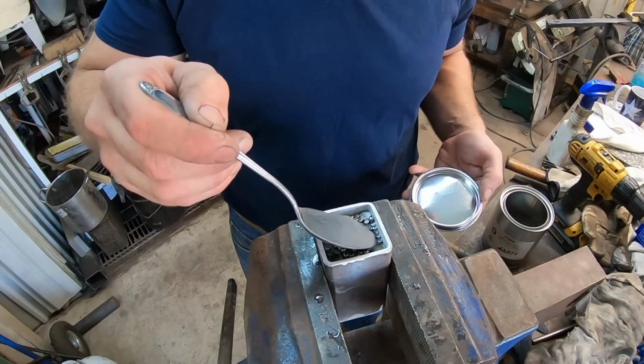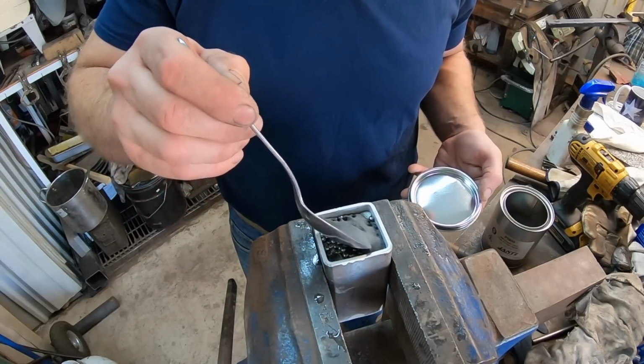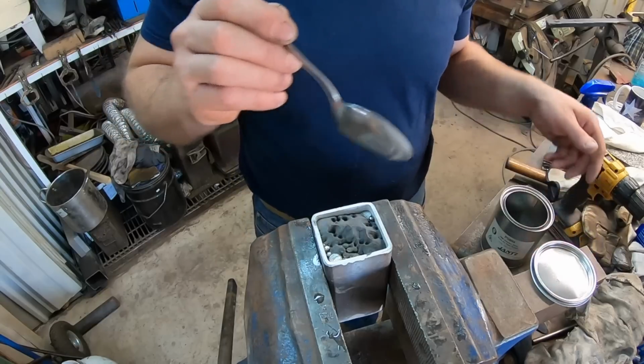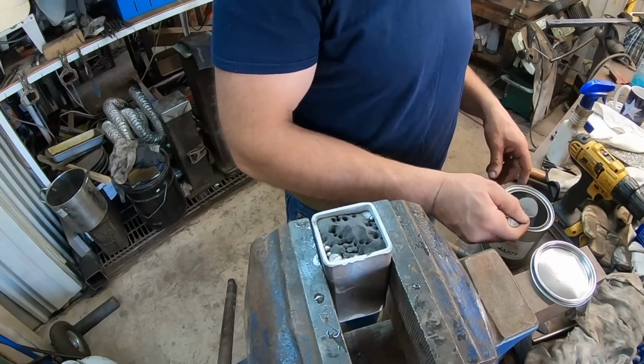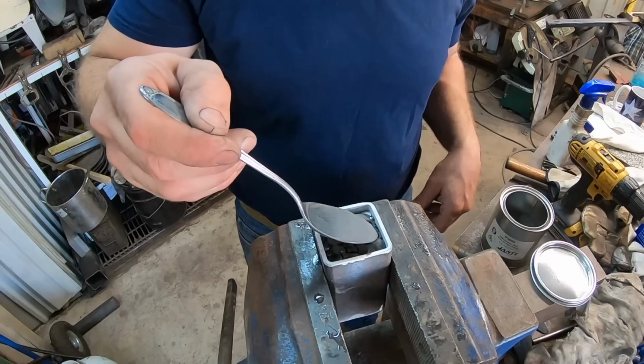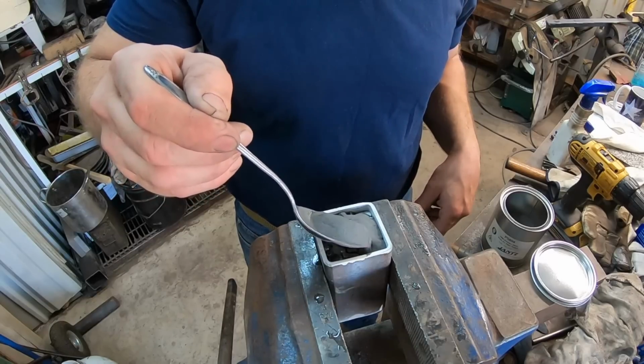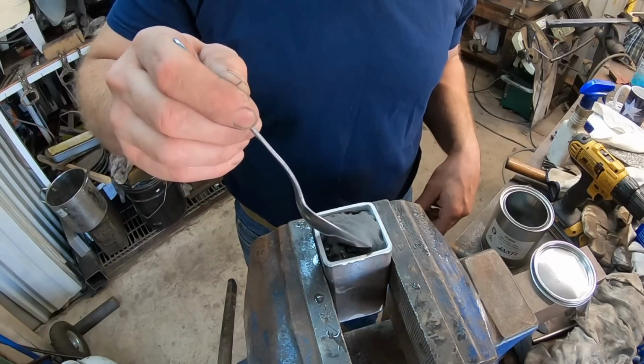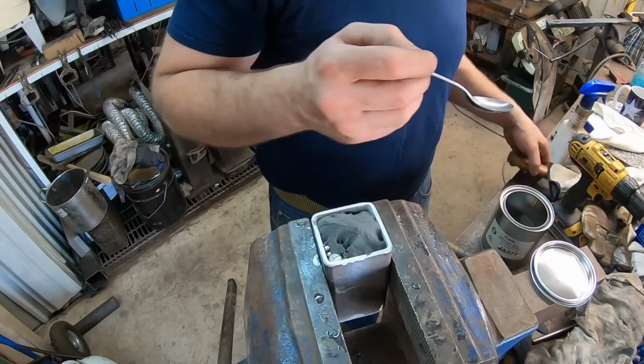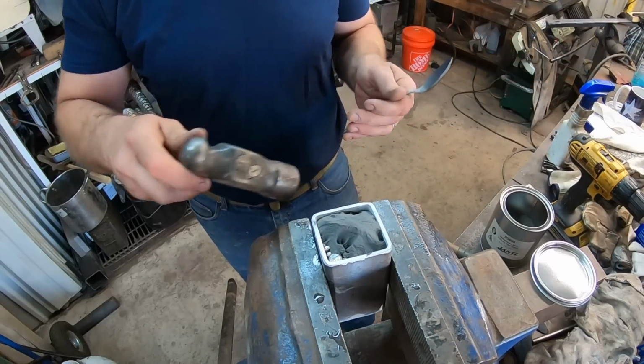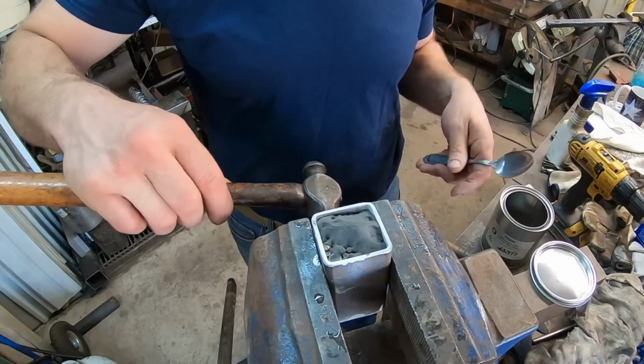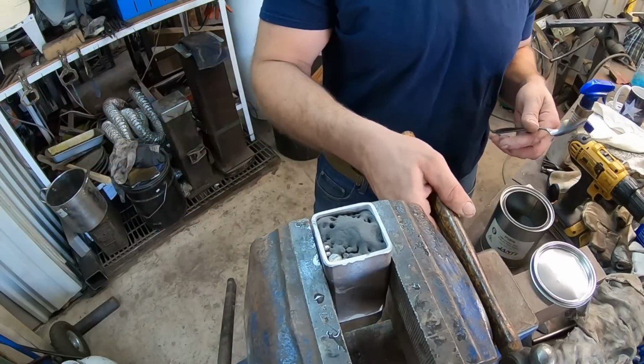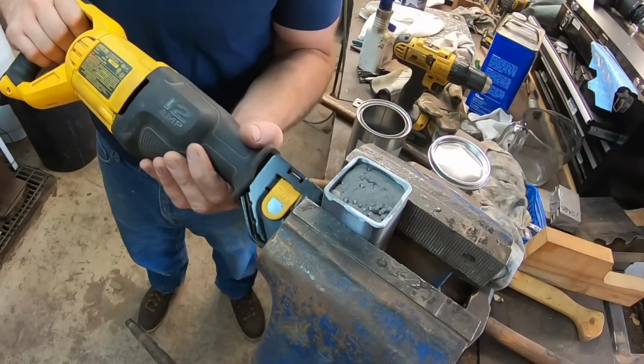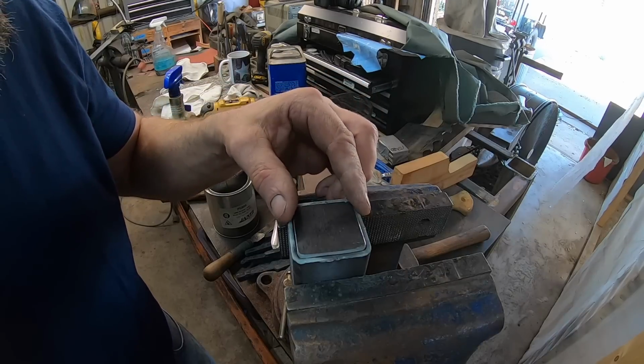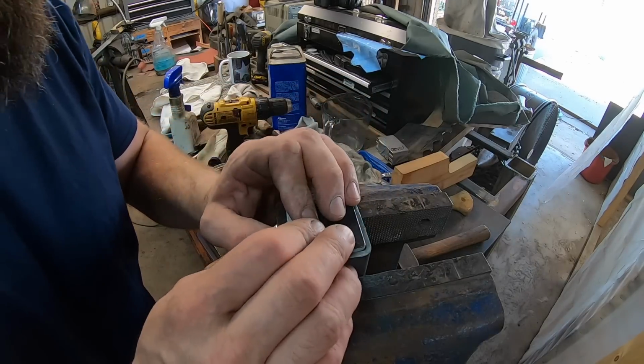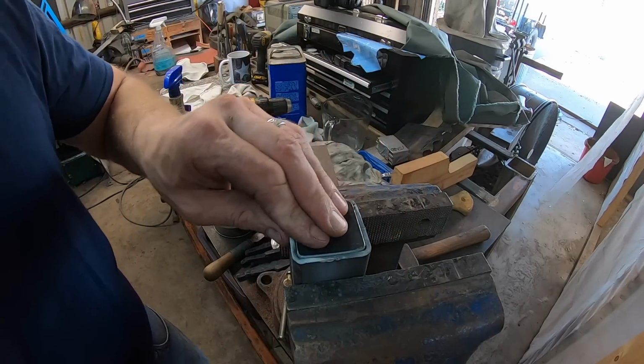Now I'm going to fill up all of the remaining voids with 1080 powdered steel, which contains 4% nickel powder mixed in the powdered steel. Quite a lot actually goes in there, even though the canister already looks pretty full. Multiple spoonfuls of this powdered steel go in, and then making sure that it is packed down as tightly as possible so there are no voids or air pockets in the canister.